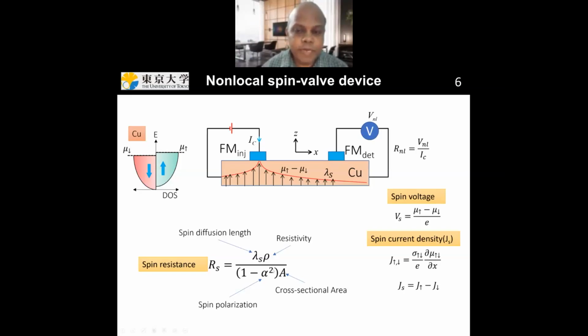For example, if you have a non-magnetic material, for example copper, the spin polarization is 0 because it's not magnetic. So it will depend only on the resistivity, the cross-section area and your spin diffusion length. But if you have a magnetic material, then you have a finite spin polarization, so you have to consider all these concepts. And usually, for example, in copper, the spin diffusion length is very large. So that's why you have a very large spin resistance. And for example, in permalloy, the spin resistance is lower because the spin diffusion length is very, very small, around 5 nanometers. So it is very counterintuitive. For example, permalloy electrically has a very large resistivity compared to copper. But in terms of spin resistance, copper has a higher spin resistance compared to permalloy. So you have to consider the spin diffusion length, not only the resistivity.